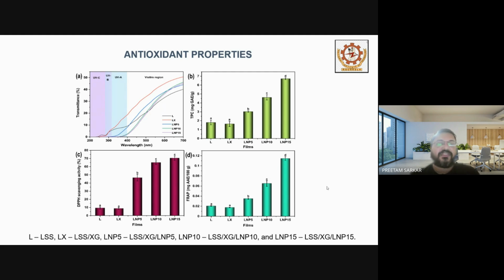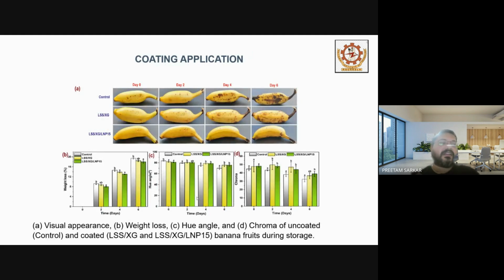Okay, so we're going to prepare films which are antioxidant. Not antimicrobial, but antioxidant. Therefore, we have performed different parameters like TPC, total phenolic content, DPPH scavenging activity, and FRAP assays, which are multiple assays to quantify the amount of antioxidant activity. Then finally we apply the film to the fruit for the banana coating.